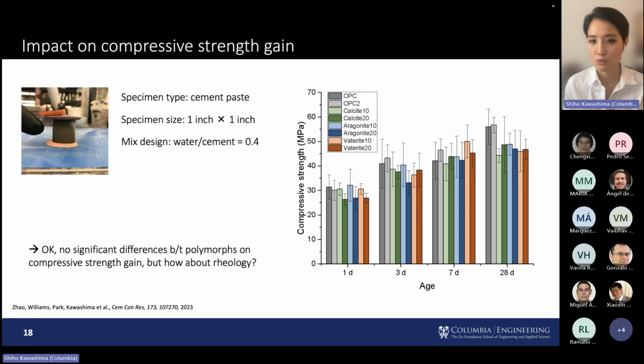There's no real measurable effect, at least by the method that we use, which was 1-inch cylinders due to limitations in the material that can be produced. But as a limestone filler, this is an expected trend, so it's not behaving any differently from what we use today. And with PLCs, with Portland limestone cements, we know that to achieve the comparable strength gain or the target strength, we can apply grinding, right?